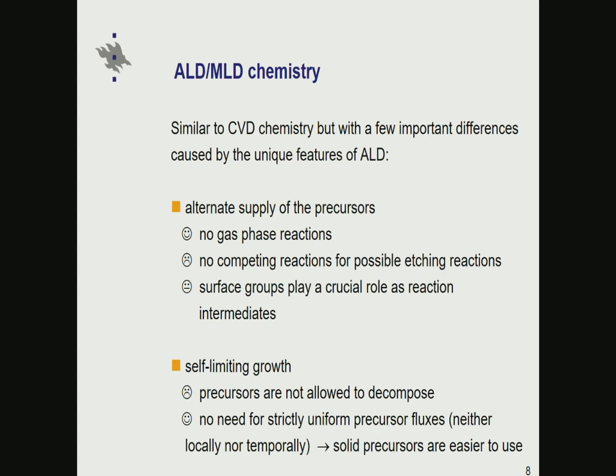These are actually consequences of the special characteristics of ALD, so alternate pulsing and the requirement to have self-limiting, self-terminating surface reactions. So with alternate supplying of the precursors, the good news here is that we don't need to worry about gas-phase reactions. In CVD they may start creating particles if they occur too readily. On the other hand, the negative news here is that we don't have competing reactions if there are possibilities for etching reactions to take place. I will show you some examples of those later.